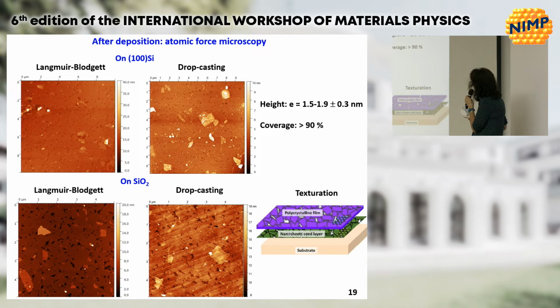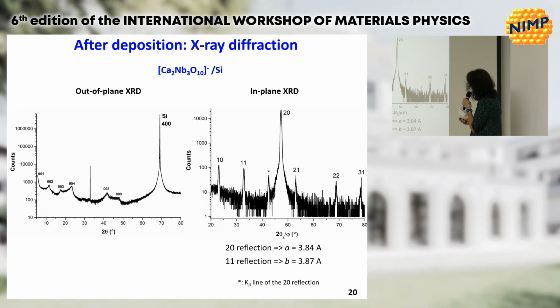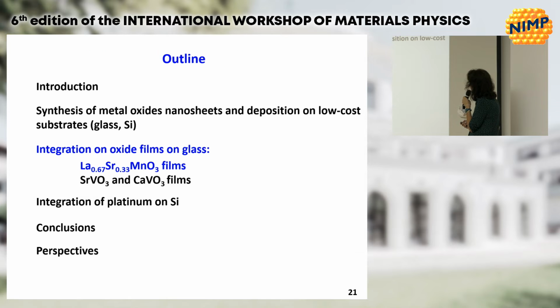So it means that when we grow the oxide film on top of it, we will get a texturation of the film. We can also characterize the nanosheets after the deposition. By out-of-plane X-ray diffraction, you have nothing really relevant, of course. But by in-plane X-ray diffraction with a laboratory diffractometer, we can have nice peaks, and it confirms the crystalline character of the nanosheets. So now I will show you the result of the integration of oxide films on glass.